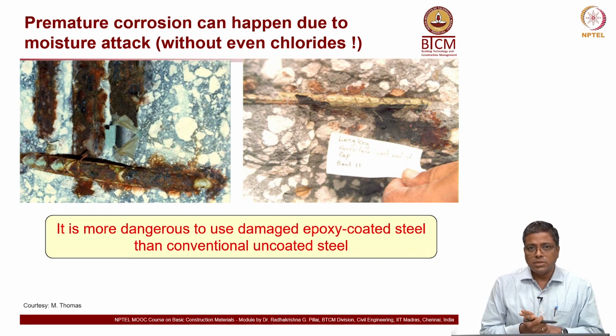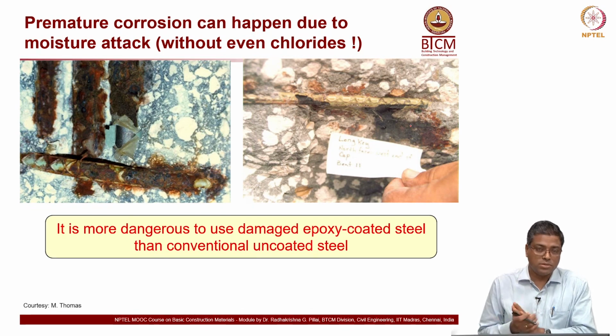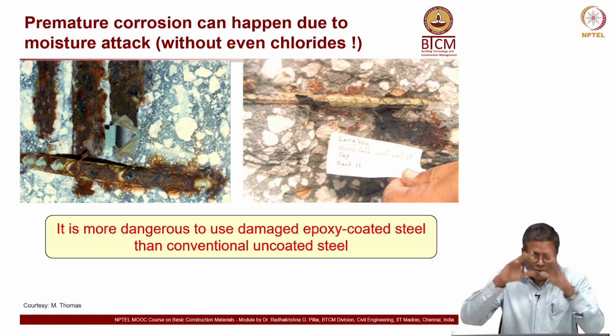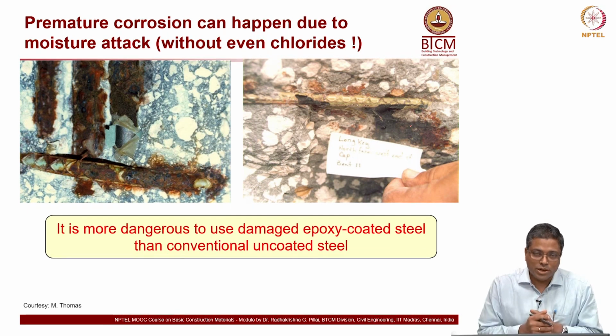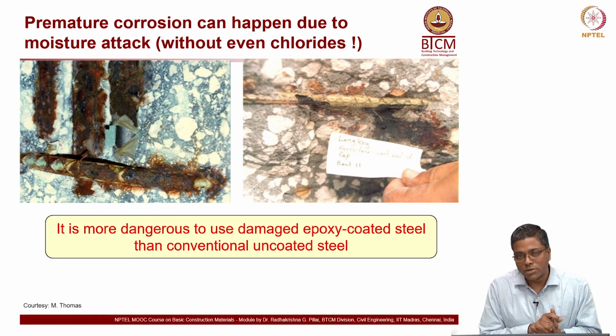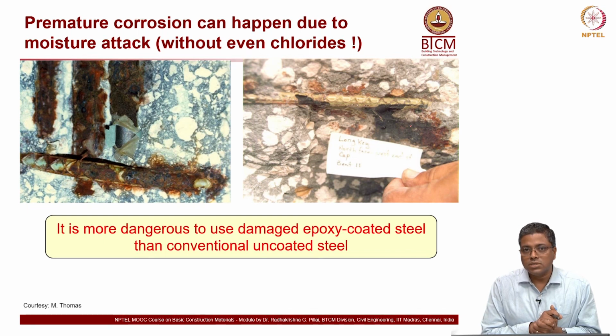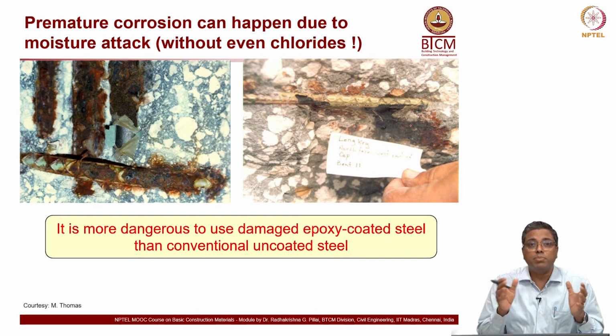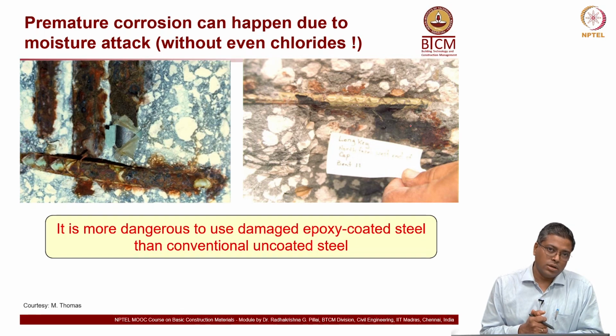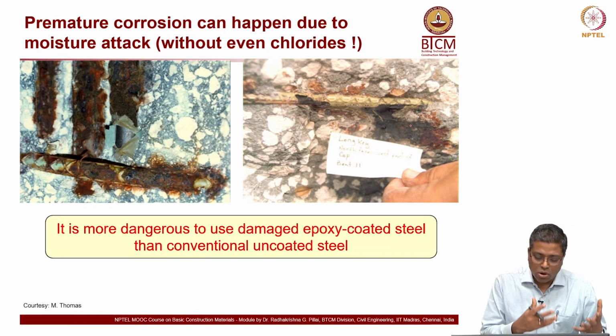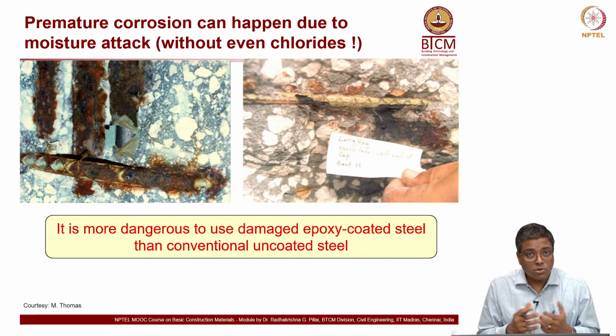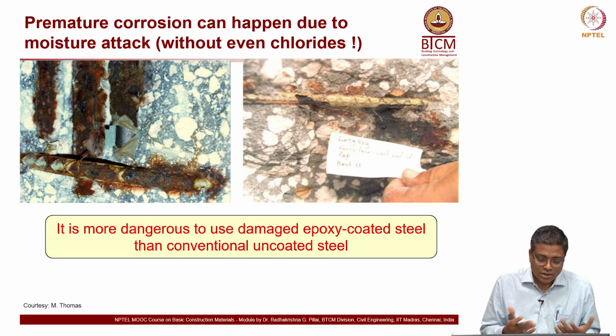So, the message here is we should not use these bars unless we can ensure that they are taken care of like babies. With babies, we make sure that when we go out in the sun they are protected and we handle them very carefully. These rebars also need that baby-like treatment, otherwise they will not perform, they will not have any corrosion resistance, and in fact their corrosion resistance is going to be poorer than an uncoated reinforcement. So, you don't waste money, because this kind of coated rebar costs about 20 to 30% more, and if you do that and you don't get the return, then it is of no use.